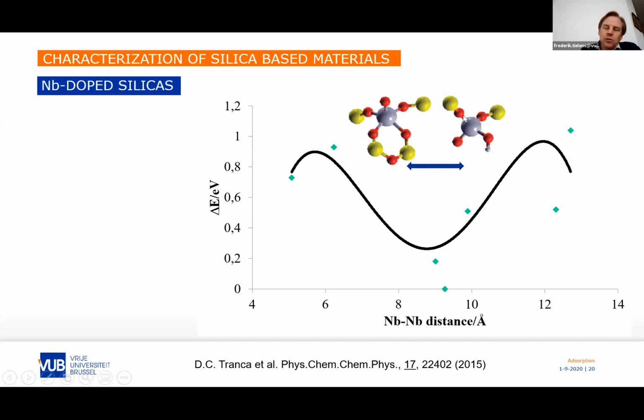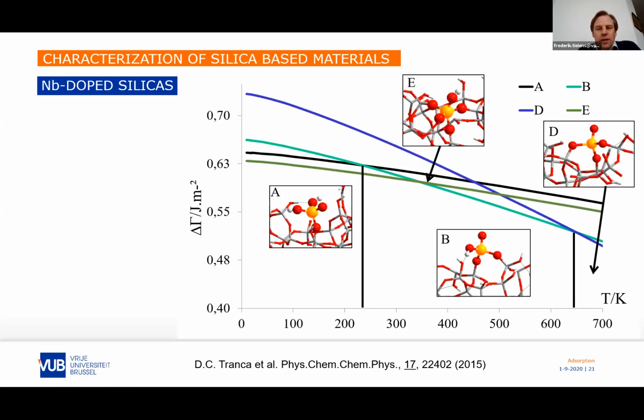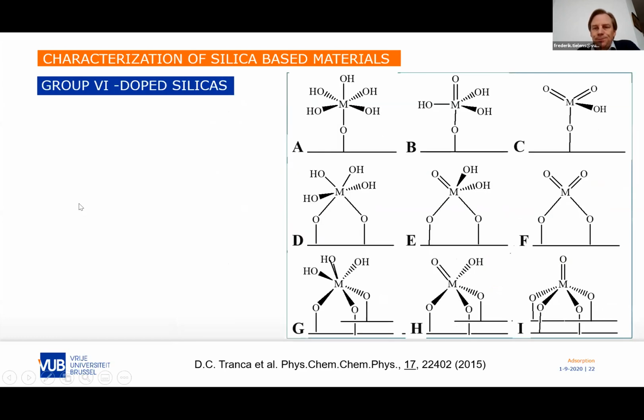We should also say that if you have a pair of niobiums, they also show a different coordination. Experimentally, it is also shown that you have a Lewis acid and base pair, O minus and niobium plus side. Here again, the phase diagram was made in the same way. Once you have the different structures and the degree of hydration, you calculate the energy and you can make a surface energy of that, and you plot it in this kind of diagram.